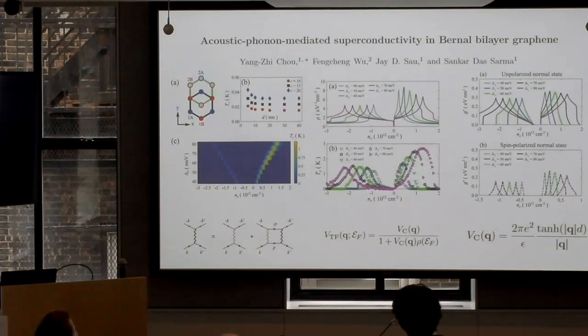This is good, because things should depend very strongly on band structure, and the band structure changes completely. These are band structures. Again, we have to calculate band structure. I've become a band theorist, I'm very happy. I have persuaded my younger collaborators to become band theorists. So this is the band structure. It's very different from what it was before. I'm summarizing the whole result here for you, because I was not sure how I'd do with time, because there's one other thing I want to talk about. The calculation is very similar to the last one, but there is one difference here, because TC is so low. Adding mu star in the last calculation changed our TC from 4 Kelvin to 2 Kelvin.